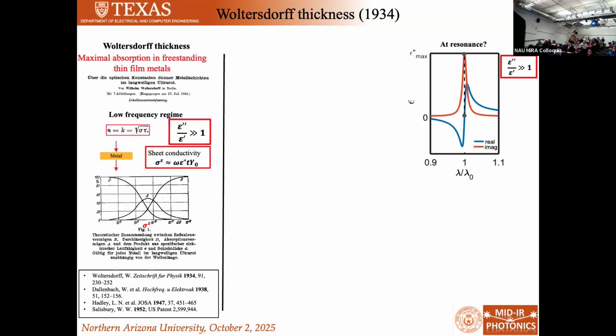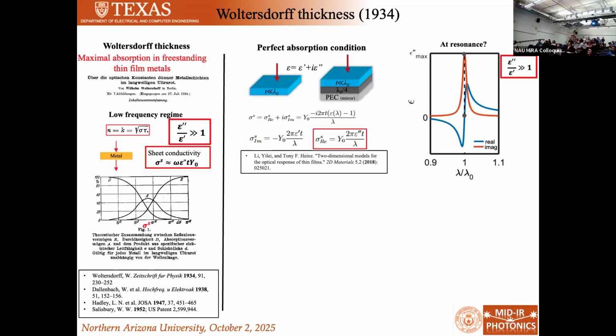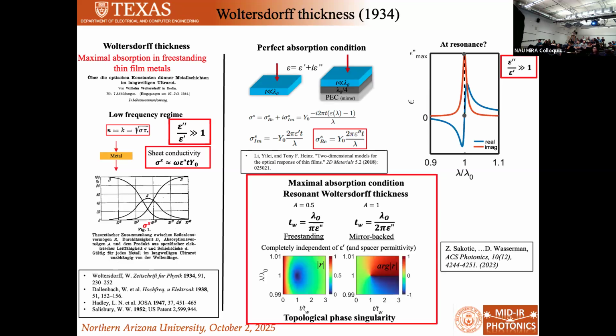And so Darko started thinking about, well, what happens if we have a thin film, but it has an absorption resonance in it? And then moreover, what happens not just if we consider that thin film, but we consider it in a very simple open cavity system where we have a perfect electrical conductor and then some spacer, right? And so it turns out that you can calculate what we call a resonant Woltersdorff thickness that shows you how thick or thin that material needs to be to absorb all of the light incident on it, whether it's freestanding or whether it's mirror backed.